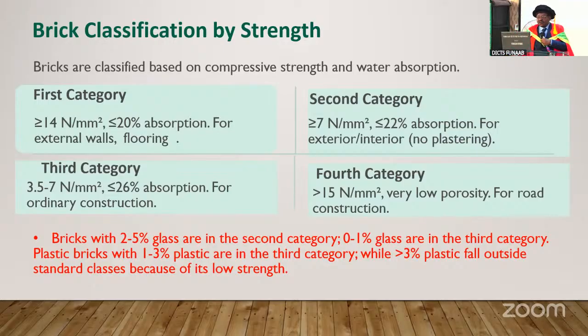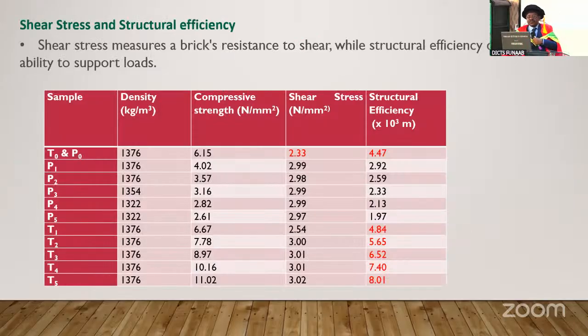From our result, the bricks with 2 to 5% glass are in the second category. The one with 0 to 1% glass are in the third category. Plastic bricks with 1 to 3% plastic are in the third category, while the one greater than 3% fall outside the standard classes because of its low strength. We also look at the shear stress of the structure.